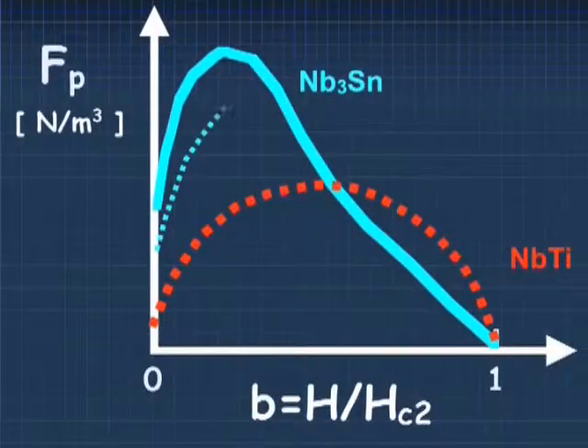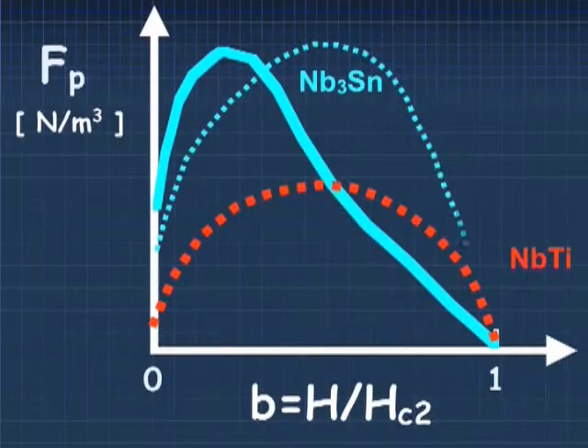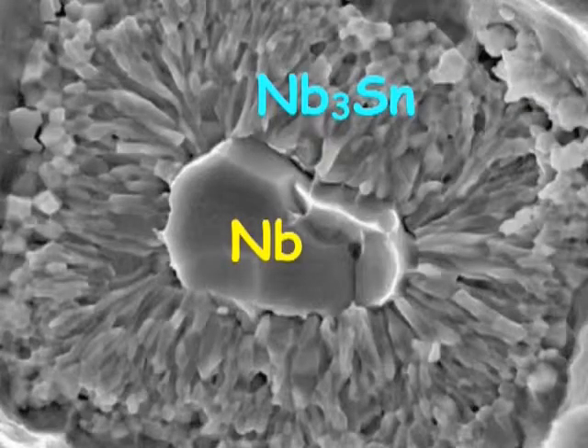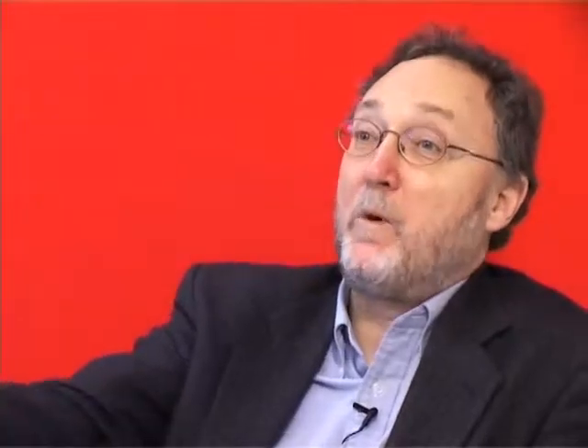The future, therefore, of niobium-3-tin is dependent upon the development of elongated pinning centers, which make the microstructure look rather more like niobium-titanium than this columnar picture in niobium-3-tin. So that's what we mean by flux pinning.